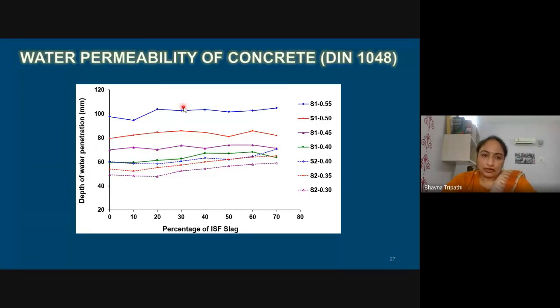And if there is some plus and minus, that is, a deviation, then the deviation was within 15%, which is not significant. We cannot consider it as significant. So largely, when we conduct a harsh test, which is a destructive test, in this test we break the specimen and we visualize the depth of water penetration.